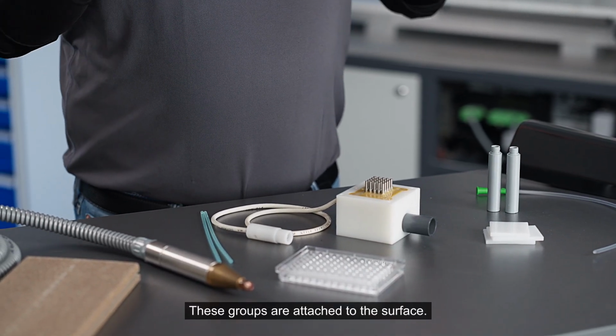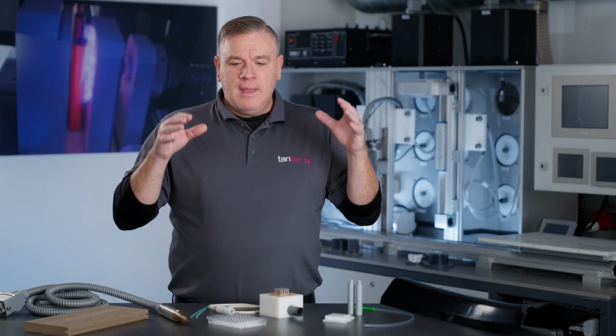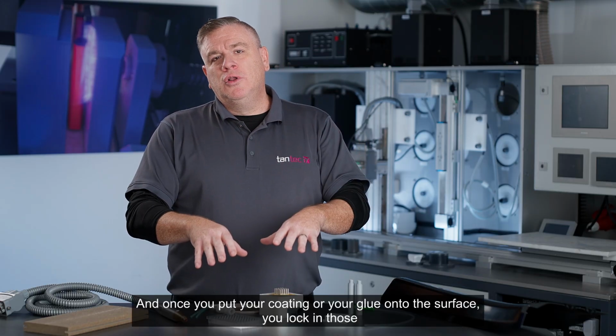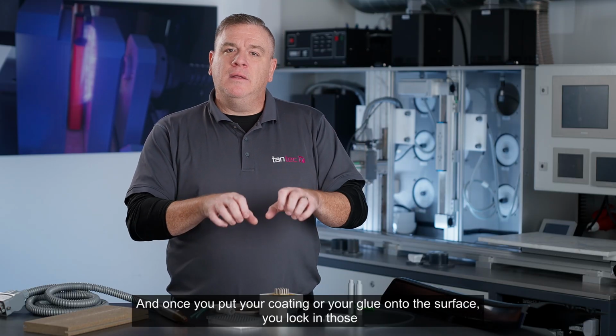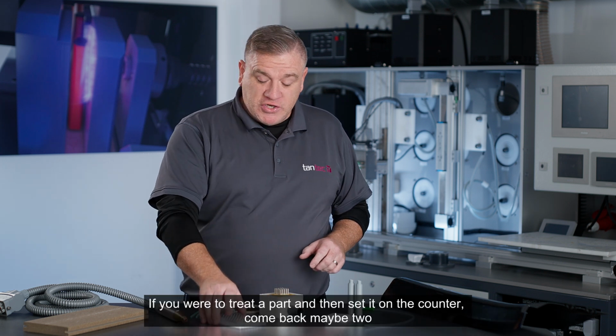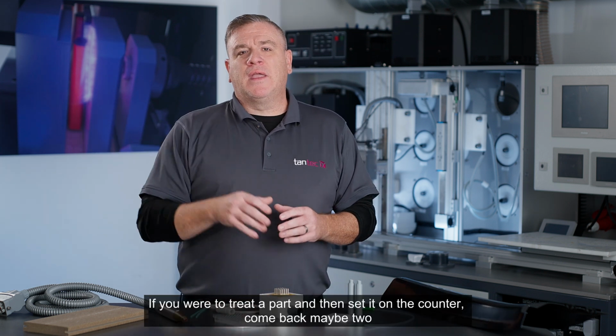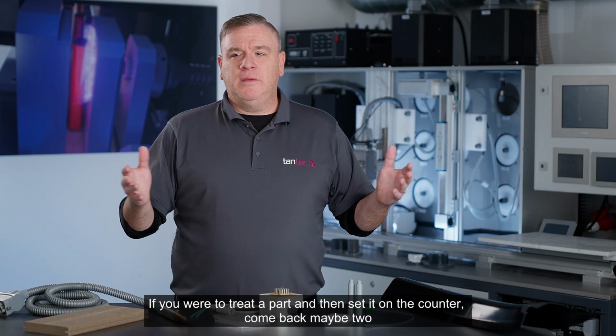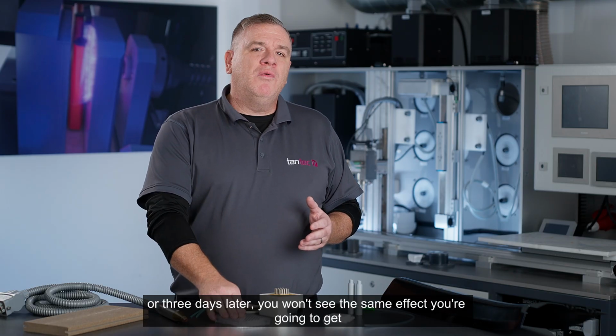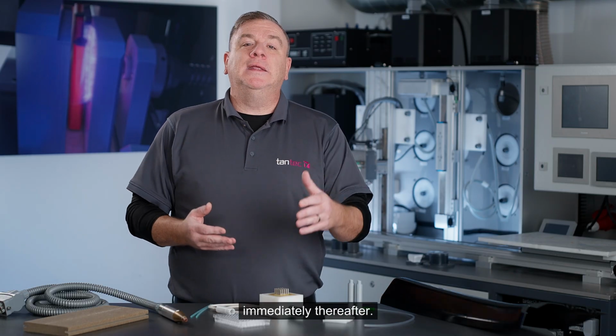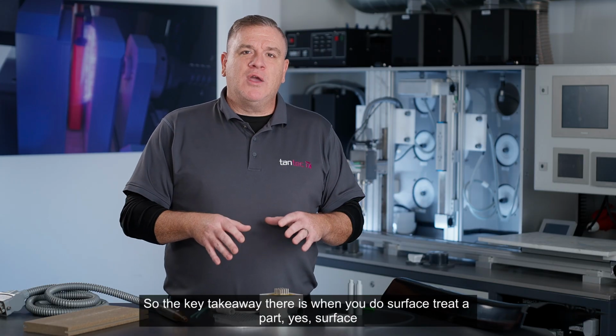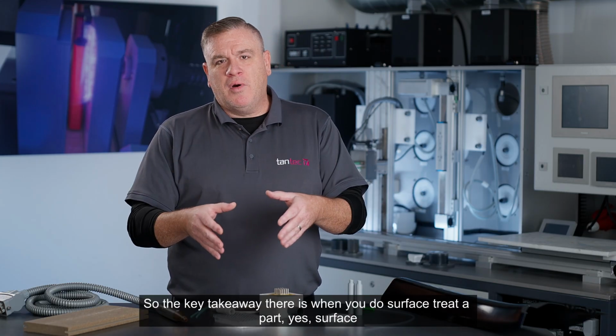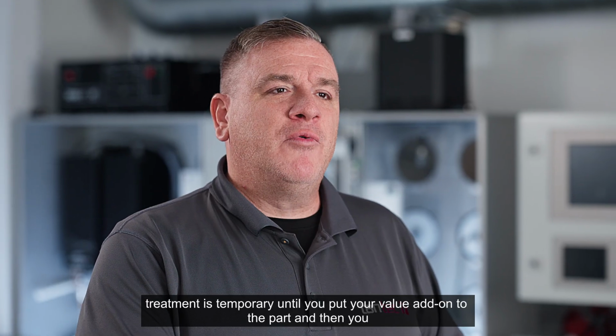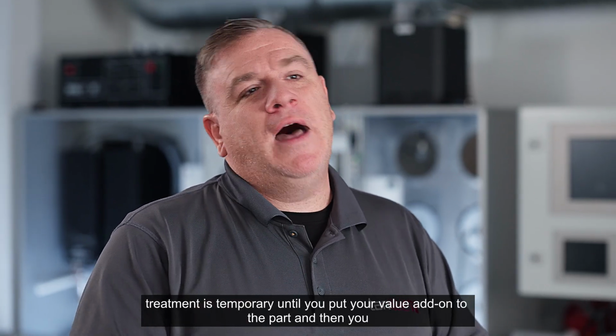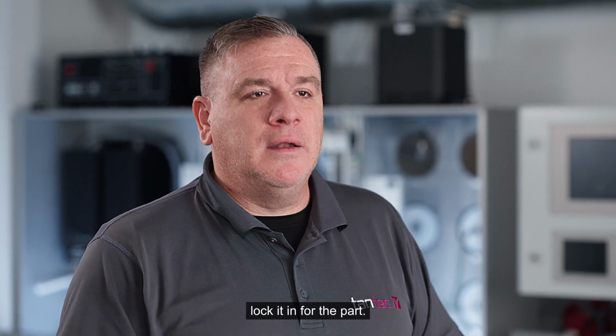These groups are attached to the surface, and once you put your coating or your glue onto the surface, you lock in those attachments. If you were to treat a part and then set it on the counter, come back maybe 2 or 3 days later, you won't see the same effect you're going to get immediately thereafter. So the key takeaway there is when you do surface treat a part, yes, surface treatment is temporary until you put your value add onto the part and then you lock it in for the part.